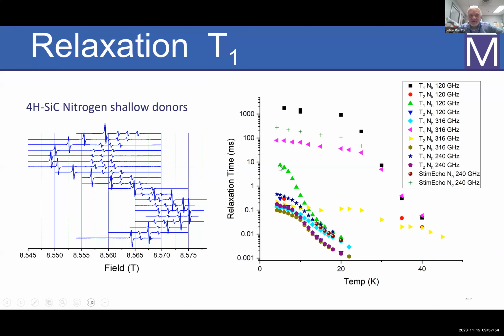And for the hexagonal centers, the T1 is actually a little faster, but you get the same kind of behavior. So your T1 at 120 gigahertz is 10 milliseconds for that center. But then if you go to 240 gigahertz, it is about 0.6 milliseconds. So you get this really strong dependence in your T1 relaxation. And this is just because this is the contribution from the direct process. Your phonon spectrum has a much higher density of states at these high frequencies. So you have more phonon states available to relax to, and that then induces a much faster relaxation.